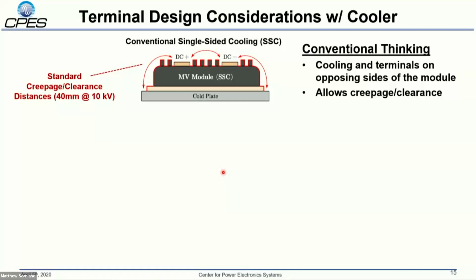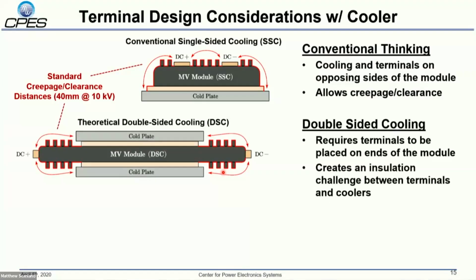Now this picture starts to get a little strange once we add a second cooling surface on the top. So now we need to move the terminals to the side, and we have to honor that creepage and clearance distance between the terminals and the base plate. So this starts to set a lower bound on the power density we can hit. You can imagine as the width of this cold plate starts to go to zero, the overall length of our module is about twice the creepage distance. That's the lower bound on what we can do.